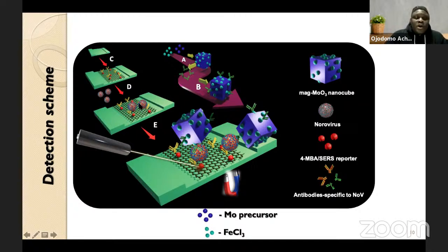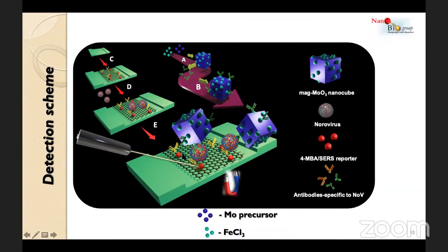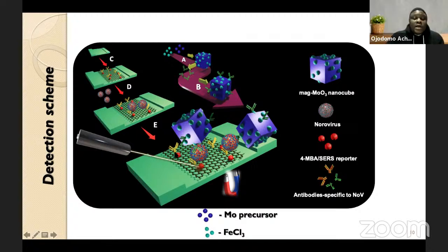So one of the hotspot engineering concepts that we deployed in this work was, rather than the usual method of conjugating the SERS reporter or the Raman reporter to the nanocubes themselves, we conjugated them on the graphene substrate. This was aimed at giving us some first-hand experience, rather than having a direct enhancement from the nanocubes that are being attached. We decided to attach the Raman reporter to the substrate so that we can have an effective dual effect. One from the target nanocube, which will be sandwiched between the virus and the substrate. Then also the contribution from the graphene substrate to the SERS effect, or the SERS signal of the reporter.